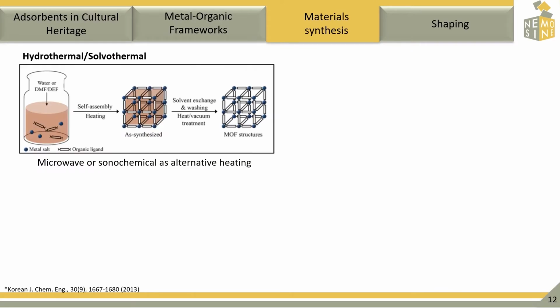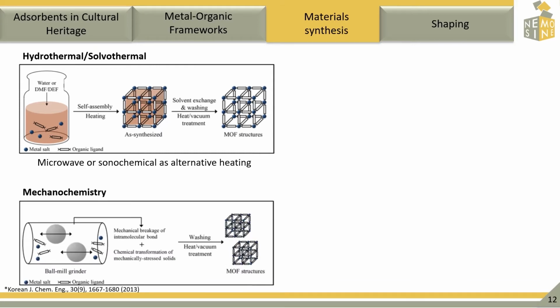So how are these materials obtained? These materials can be obtained with different synthetic types, as for example with solvothermal, where the reaction is done in an autoclave with high pressure and high temperature and usually requires aprotic solvents, while in the hydrothermal we only need water. These conditions favor the dissolution of certain aromatic ligands that are usually insoluble, and this promotes also the reactivity between the precursors. This is the case of the synthesis currently being used to form UiO-66-2CF3.